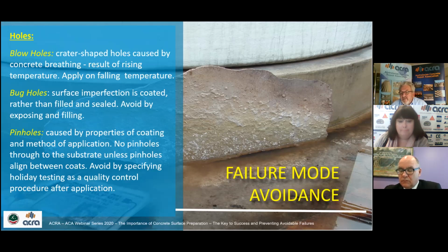A bug hole, as you can see, is more like an eye socket. So what you see at the surface of the bug hole isn't the actual size of the bug hole. Once that's prepared, the bug hole opens up, and that's what we're saying there. We fill that before we put any coating over the top of it.